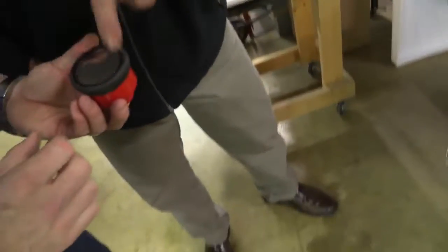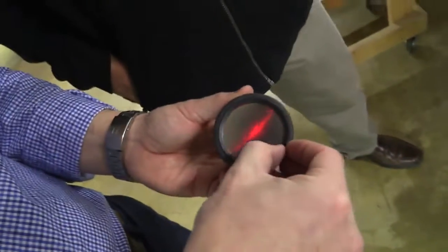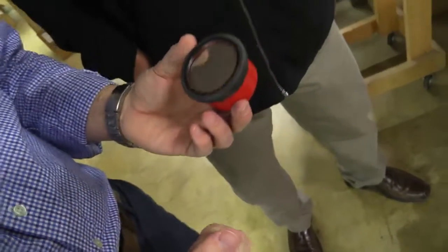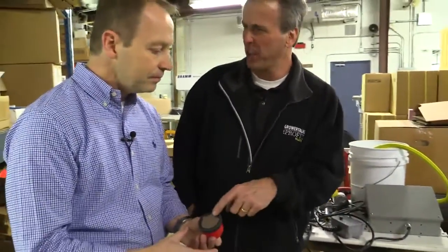This piece that we've recently added actually has an injection molded piece and rubber as well. So there's two pieces going on here. Exactly. It's actually molded together. The rubber is molded over the plastic piece that's injection molded. What that does is now when it takes a hit, the force transfers around instead of just dampening the hit. This is making it hundreds of hits before it fails. Wow, so there's a lot of engineering and testing that goes on. Just something simple like that.